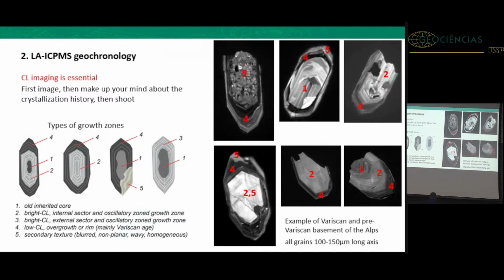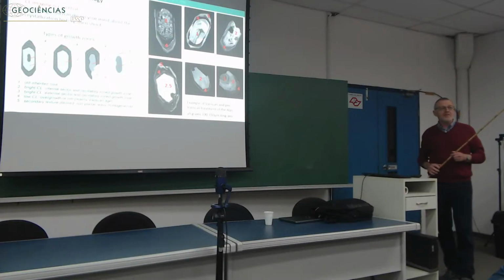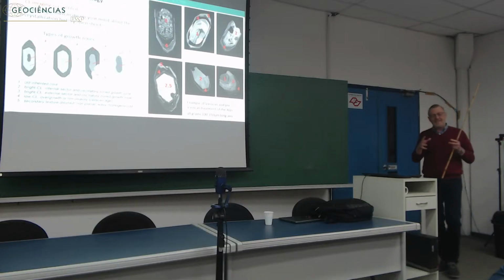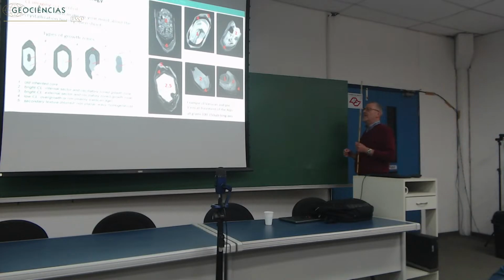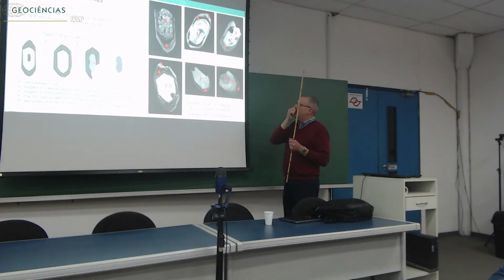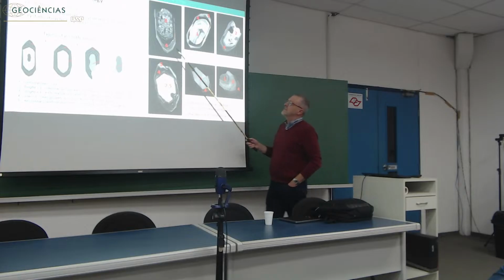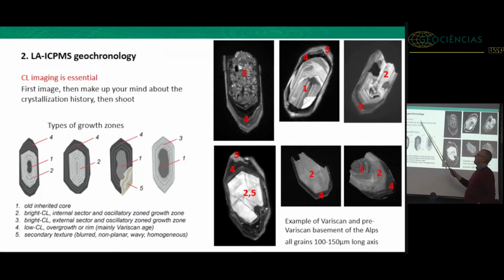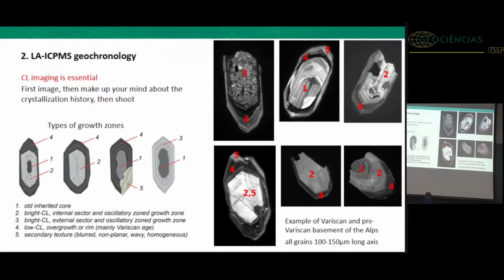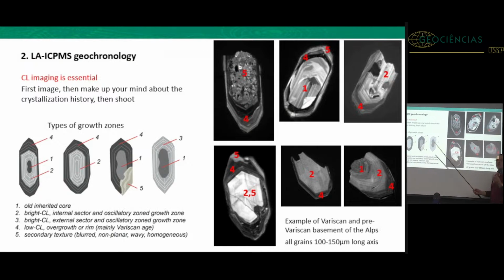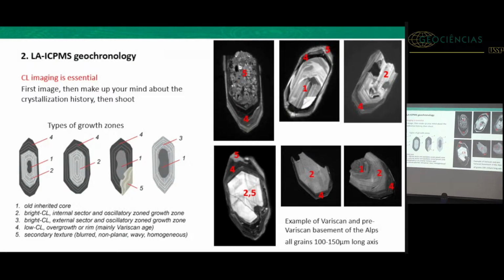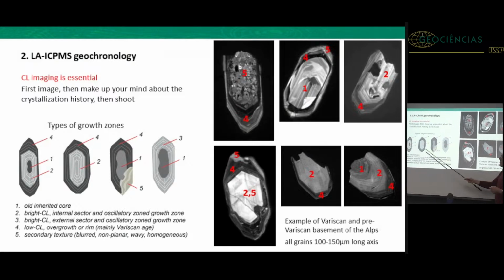So this was ID-TIMS. I think the biggest disadvantage is the bulk grain. We are analyzing grains which are complex, and we don't necessarily know what the complexity is. And with laser ablation ICP-MS geochronology, I think there is one step, the first step, simplest, which is absolutely essential. This is the imaging. So my message is that first you have to do a lot of imaging and come up with an idea how these grains formed. How many growth phases, how many resorption phases, are there inherited cores or not?